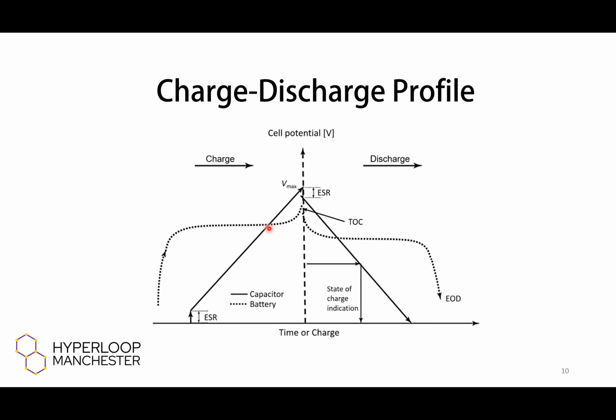But there's also to notice in this is a potential difference, the voltage drop between the charge and the discharge. So when you charge your cell, you actually charge at a higher voltage than what it will discharge at. And this is because of the thermodynamics of the system. You have to have some energy barriers and also resistance, just generally resistance in the cell. Same with the capacitor up here. You've got this equivalent series resistance of an energy storage device, and that will be the resistance towards discharging.